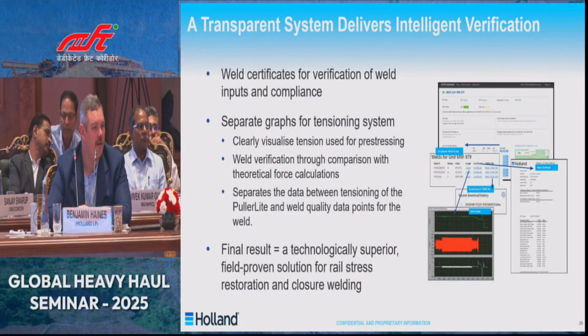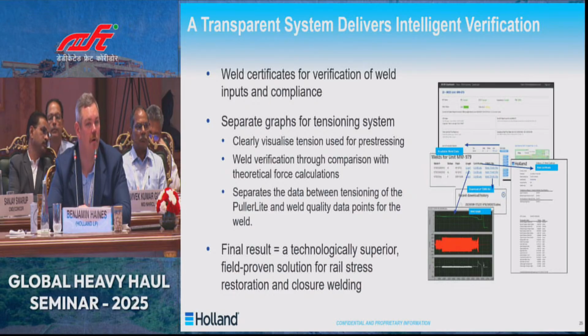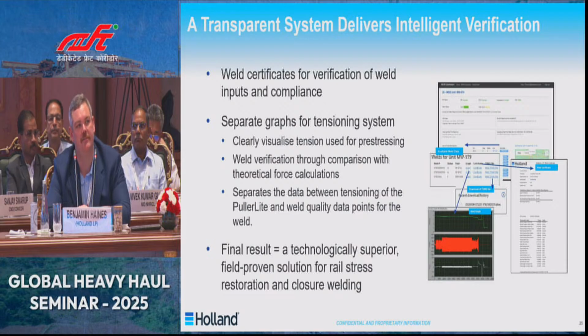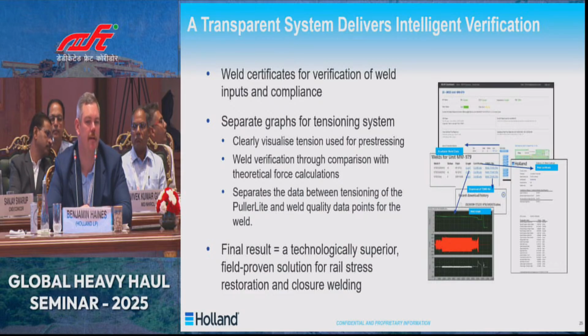So we can calculate what the force should have been required to bring the rail back to its tensile state, and then compare that to what we've actually achieved. And that's working in being transparent with our customers. This separates the data between the tensioning of the PullerLite and the weld quality. The final result is a technologically superior, field-proven solution for rail stress restoration and closure welding.